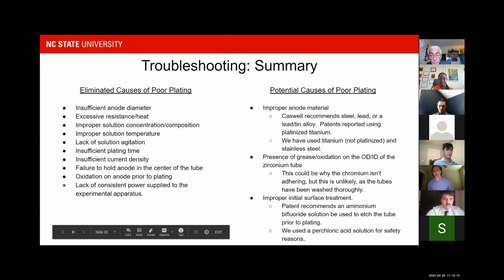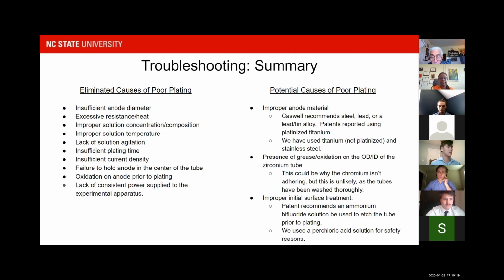So after our second experimental iteration, we regrouped and brainstormed as to what remaining cause could be causing the chromium to fail to deposit onto the surface of the zirconium cladding. We don't believe it's an insufficient anode diameter. We didn't believe it was nucleate boiling on the anode. We didn't believe it was a lack of plating time. In typical industrial plating applications with chromium, the workpieces only stay in the bath for 1 to 2 minutes, and we were plating over 30 minutes and not seeing any chromium on the surface.